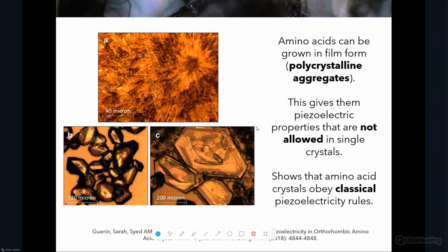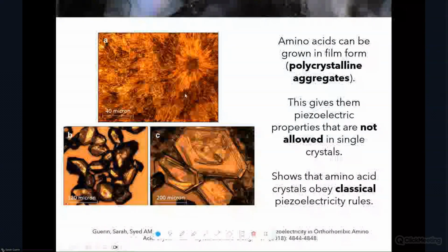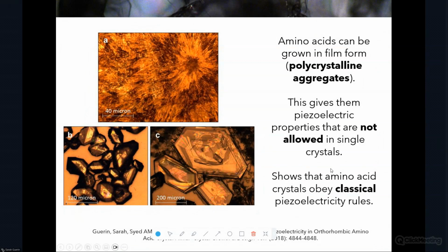So again, back in 2017, 2018, we were just seeing how these grow naturally. So this is 3 different amino acids. This is L-threonine, this is L-alanine, this is hydroxy-L-proline. And we showed that we can get these crystals to cohesively grow together in the same way that a polycrystalline ceramic would look under a microscope. But at this stage, you can see there's warpage, you can see there's gaps, you can see everything is going in every direction. So we could see that they could grow in this way. We could see that they were demonstrating piezoelectricity using the same mechanisms as piezoelectric ceramics, which was very exciting. But a lot of work had to be done to control this growth.